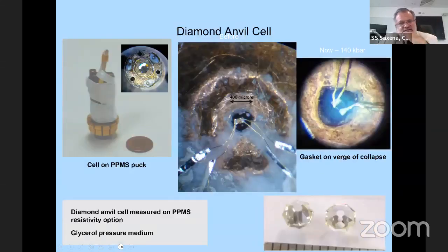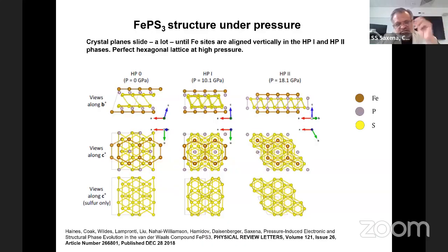Yeah. So this time we had to deploy diamond anvil cells rather than the clamp cells, the 30 kilobar ones, to study these materials. And for those who are unfamiliar with the story, we have basically a 400 micron space in which we put a small sample. We fill this space with a liquid or a liquefied gas, and then close it with the diamonds from both sides to create hydrostatic pressure, and then we can put this on a cryostat to make the measurements.